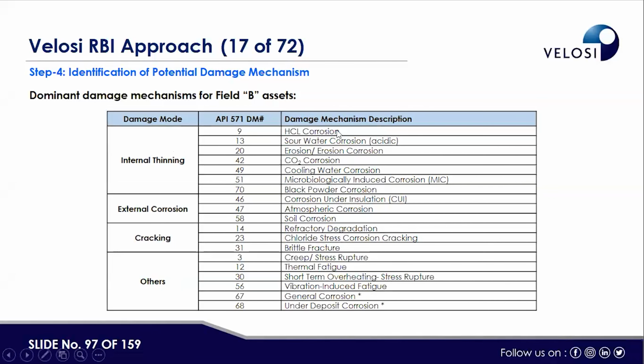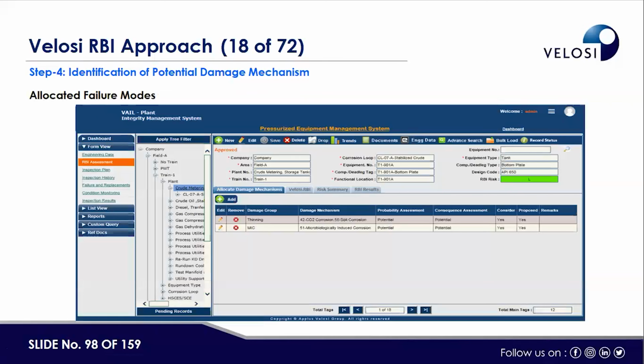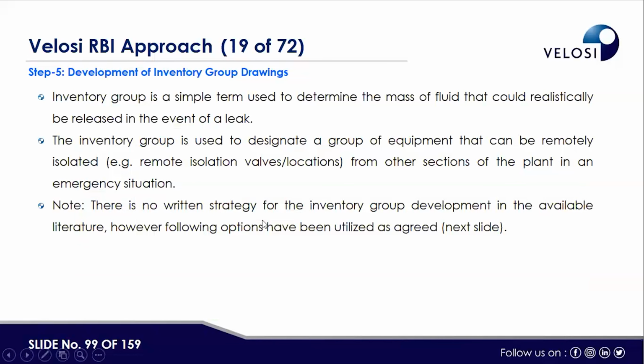HCl is coming here, right? And creep stress rupture is also coming in field B. So there are some differences, but these are the damage mechanisms which were applicable as per API 571. Here, we identified thinning and MIC for one of the components as applicable, and then